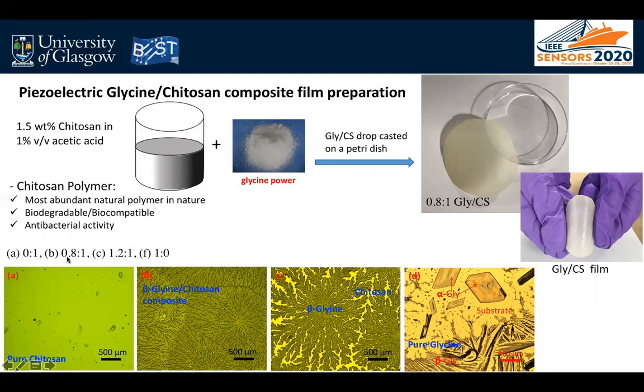We found that 0.8 to 1 is the optimum ratio of glycine to chitosan, because in this ratio we had a uniform and sufficiently flexible film.